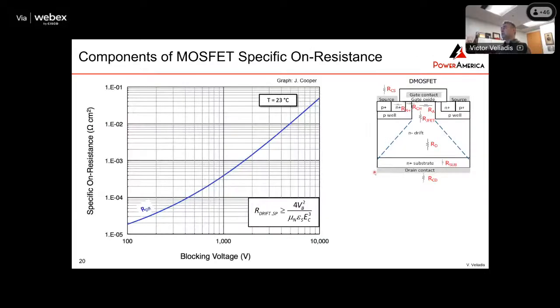So let's look at the planar MOSFETs and look at the contributions of resistance. And this graph gives you the resistance of the device versus its blocking capability. So if you make a device that blocks 1000 volts, obviously it's got a thinner drift layer to do so, and the resistance is shown here. If you make the device to block 10,000 volts, then the resistance is all the way up here as expected. So this is the resistance of the drift layer that holds the high voltage.